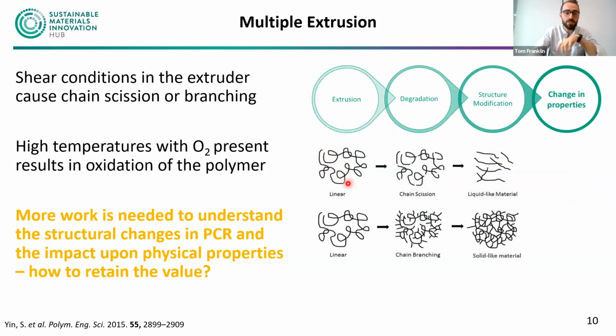So if we start with a polymer chain, it will be quite long, quite entangled. There are broadly two types of degradation that can occur. The first is that we can cut those chains up, they can become shorter, so our material becomes a bit more liquid-like, and we are modifying our chemical structure. The second is that those chains can branch, so they can find other chains and form cross-links or branches to other chains. And so you end up with a much larger network of chains and a more solid-like material, both of which will impact your mechanical properties and how it performs as a bottle. So we want to minimize degradation as much as possible.